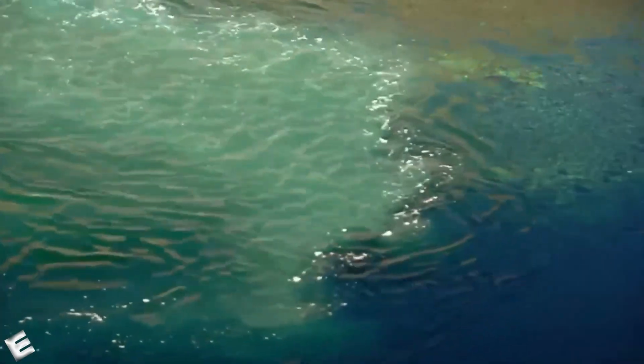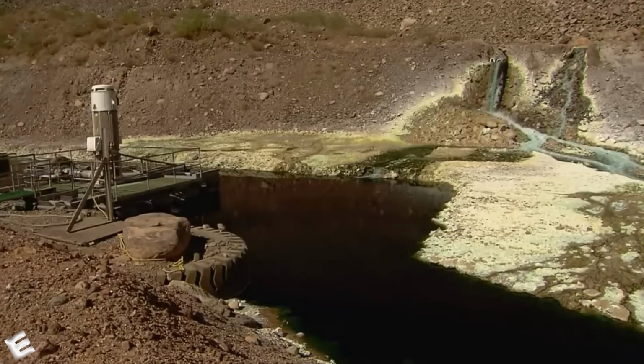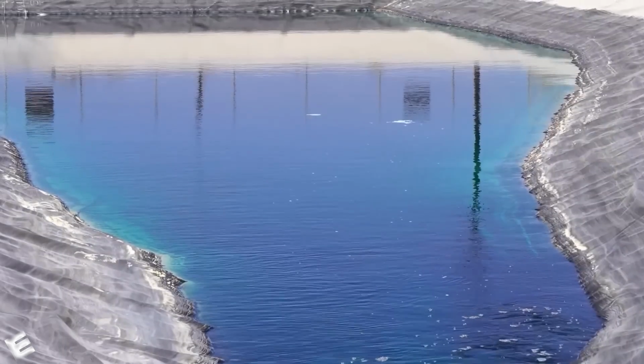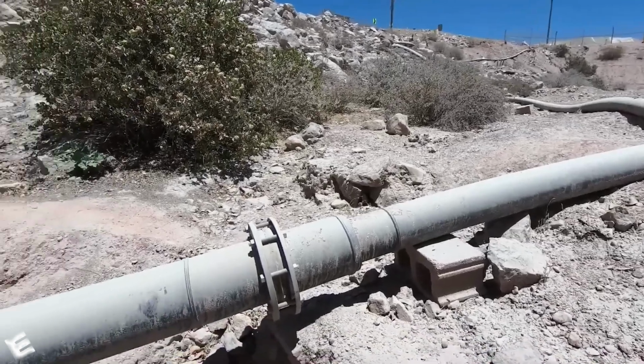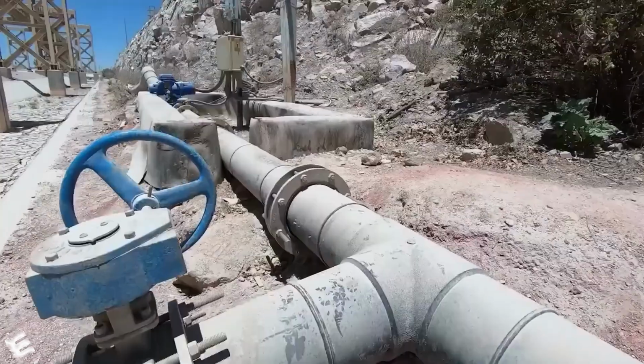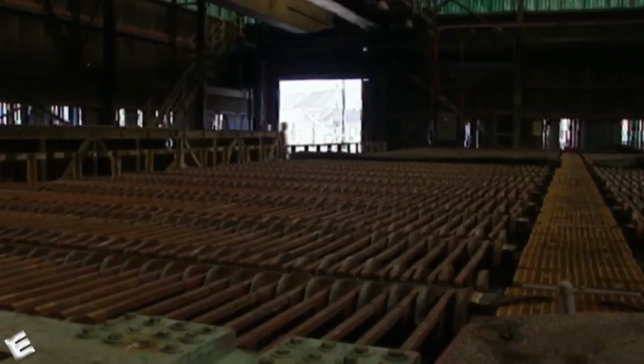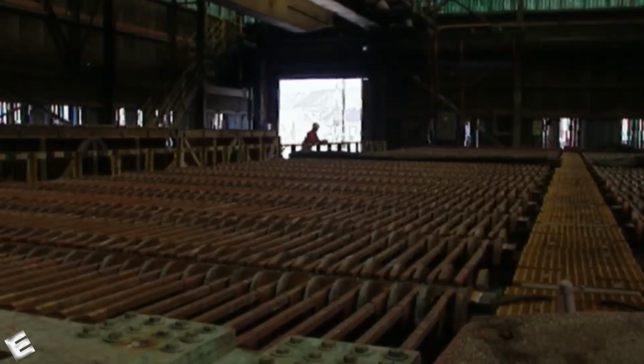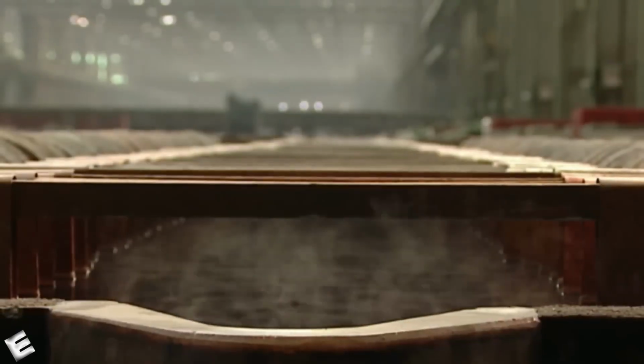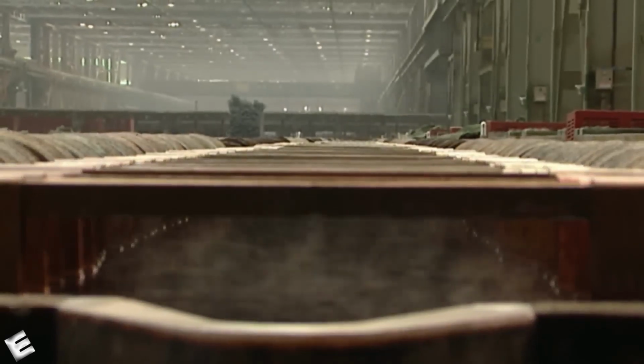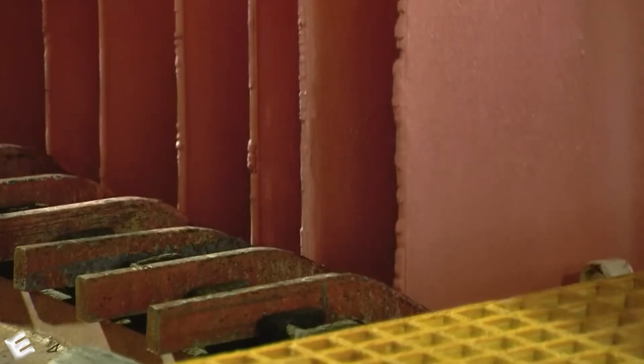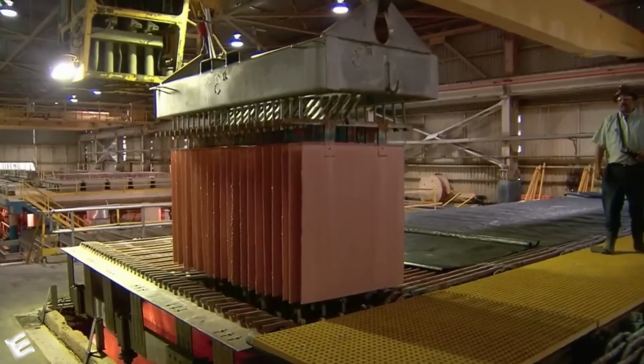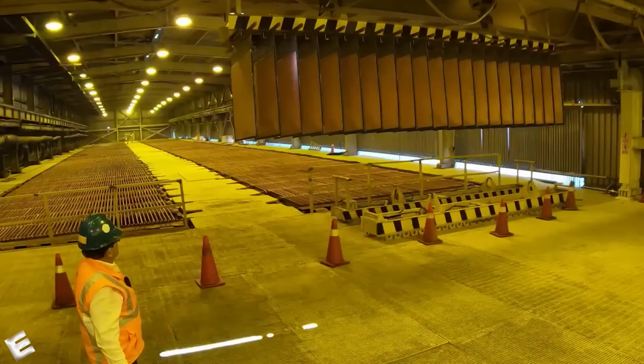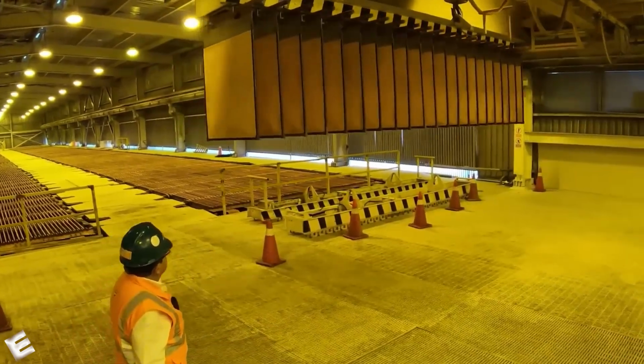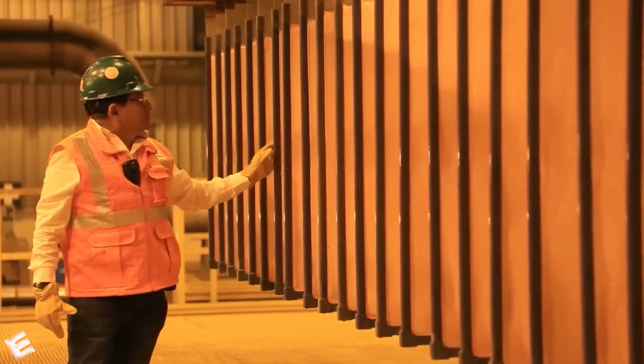In a special channel, the copper solution is combined with an organic reagent that floats on the surface. Then an acidic solution is added, increasing the concentration of copper and making it electrically conductive. The solution is transferred into a series of tanks containing thin copper plates called cathodes. An electric current is applied, and the copper ions begin to deposit onto the plates. In just 10 days, each plate reaches a thickness of 2.5 centimeters and a weight of around 125 kilograms. The purity reaches 99.99%, which is essential when copper is used to manufacture electrical products.